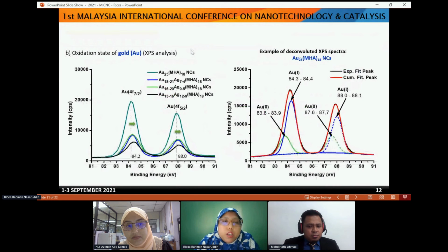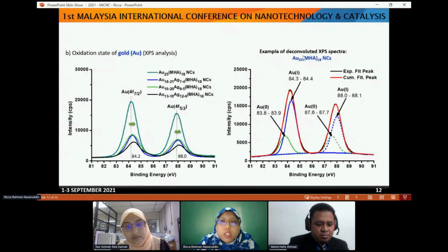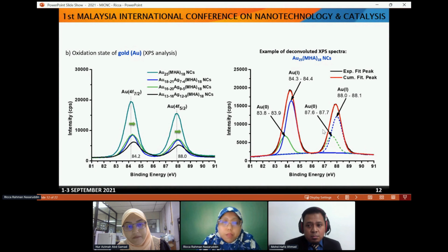So then we did XPS analysis in order to know the oxidation state of the gold. This is an example of each of them, and we also performed deconvoluted XPS spectra to identify what species of gold are inside this gold nanocluster. As you can see, we have a higher amount of gold 1 as compared to gold 0. This is an example for this Au25. I will explain more about this later with a table so that you can understand better.